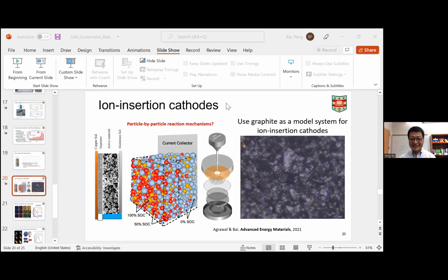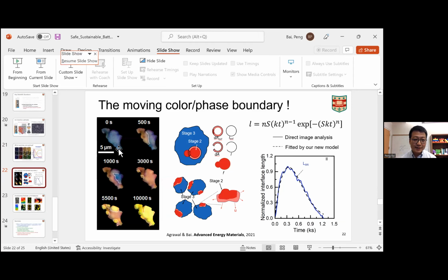And if I can expand this topic a little bit, when you see this color coming up, you can see here the initial blue color, and we start to have some orangish red color, let's assume it's red. The emergence of this red color can be more accurately characterized by a scientific term called nucleation. It's like you start to have ice flakes in a cup of cold water, right? You have this nucleation. And even for identical particles, because the emergence of a new color involves this kind of physical process called nucleation, you have this nucleation barrier.